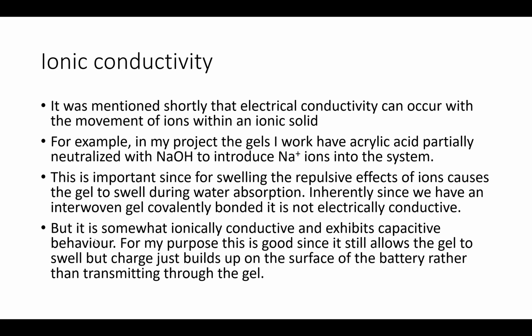Inherently, since we have an interwoven, covalently bonded gel, it is not electrically conductive, but it is ionically conductive and exhibits capacitive behavior. So because of these ions, it features this ionic conductivity, and therefore we can hold electrical charge in our gel, on one side of the gel. For my purposes, this is good since it allows the gel to swell, but charge just builds up on the surface of the battery rather than transmitting through. So that's an example of ionic conduction.